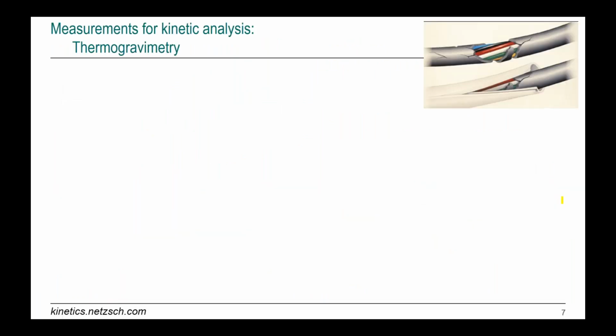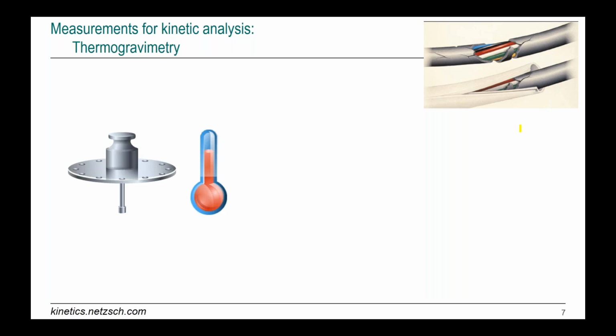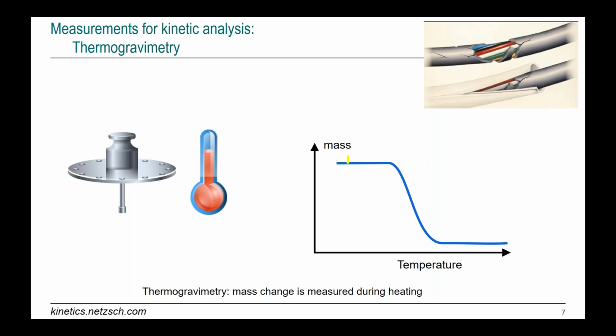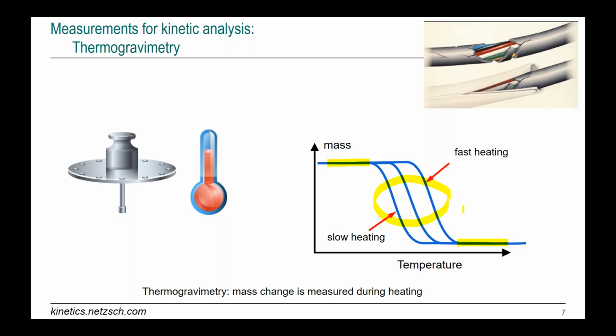How it works inside: firstly, we must have measurements that reflect information about the process. For example, for decomposition, we can use thermogravimetry, because during decomposition the mass of the material decreases. We take the thermobalance, put in a sample, heat it, and see what happens. Mass at the beginning is higher; at the end, after decomposition, it's lower—some kind of decomposition happens. We can do this for different heating rates, fast or slow, and see that initial and final mass is the same everywhere, but in the middle it's different because the process is time dependent. For different heating rates it will be different.